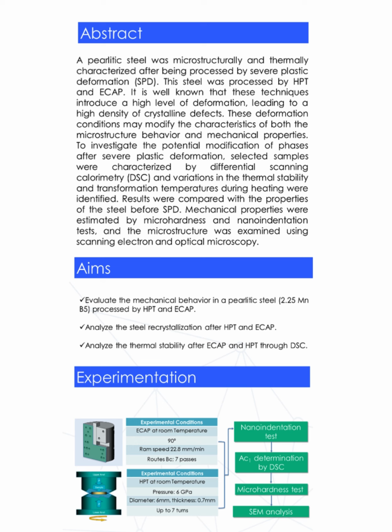Moving on to the experimentation, the steel was processed through two different routes for comparison: equal-channel angular pressing, ECAP, and high-pressure torsion, HPT. In ECAP, the samples were processed at room temperature by passing them through an L-shaped channel with a 90-degree angle at an extrusion speed of 22 mm/min. The sample was rotated 90 degrees counterclockwise after each extrusion. Each passage of the sample through the die is referred to as a pass or turn, and the samples were processed for up to 7 turns.